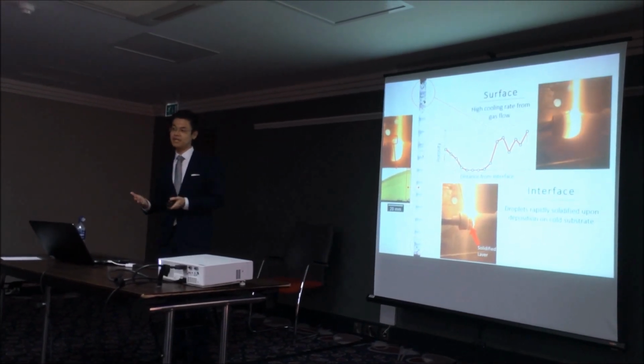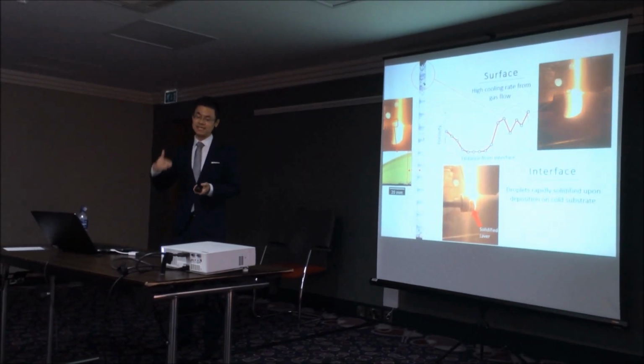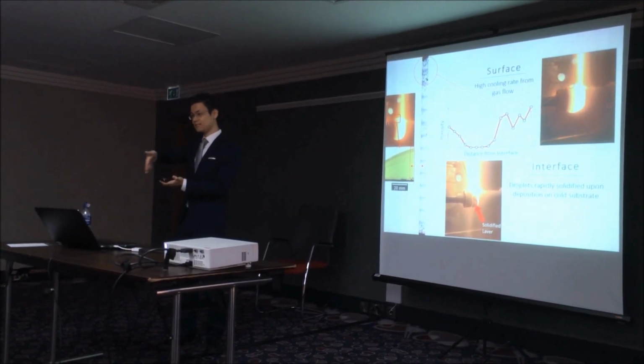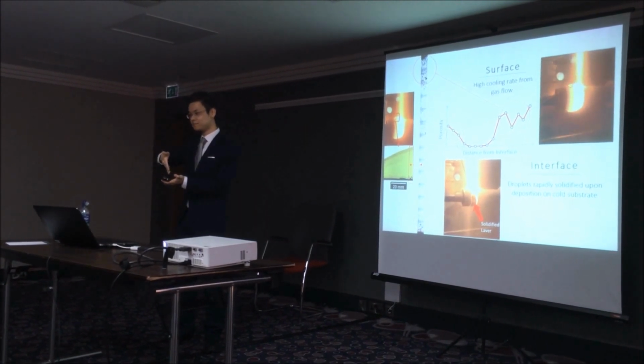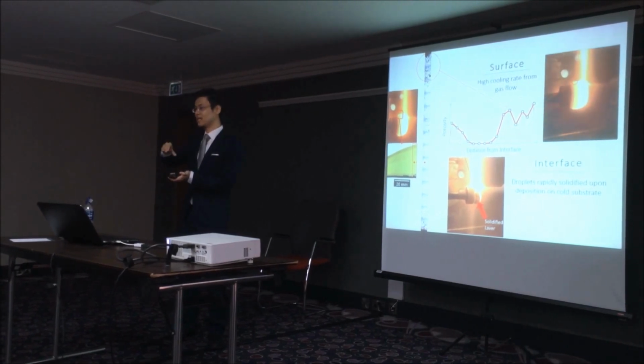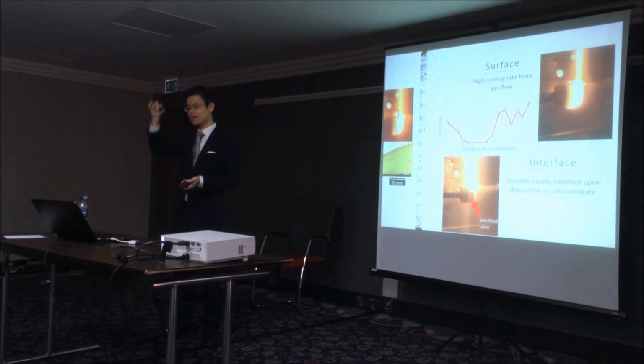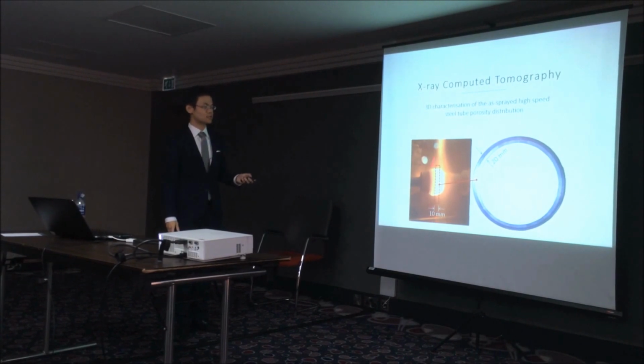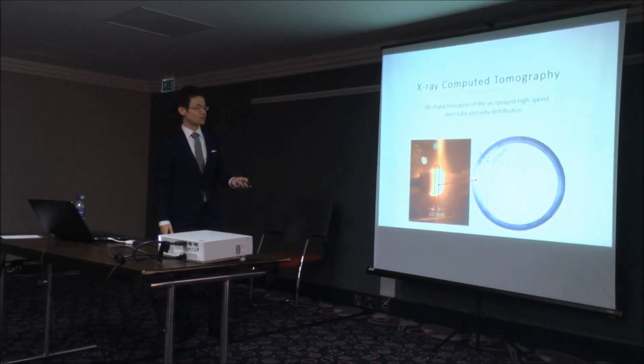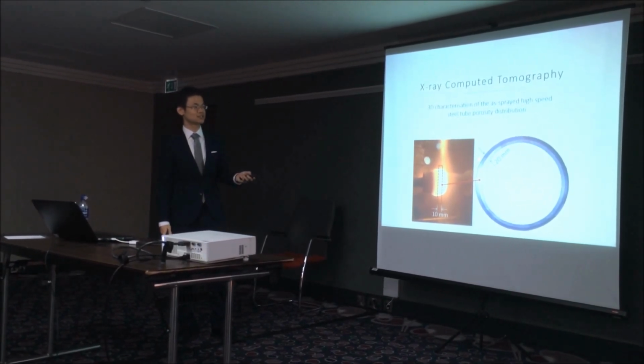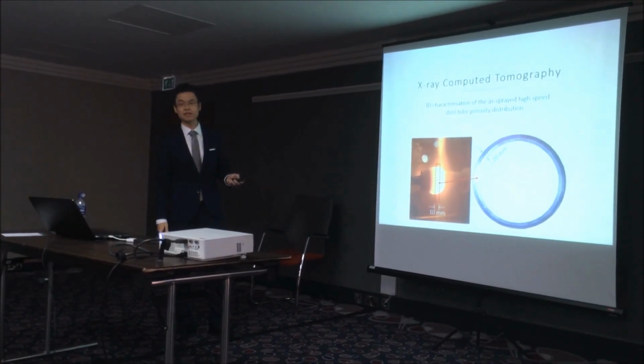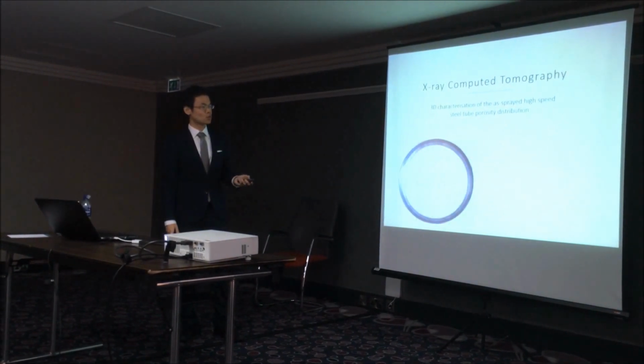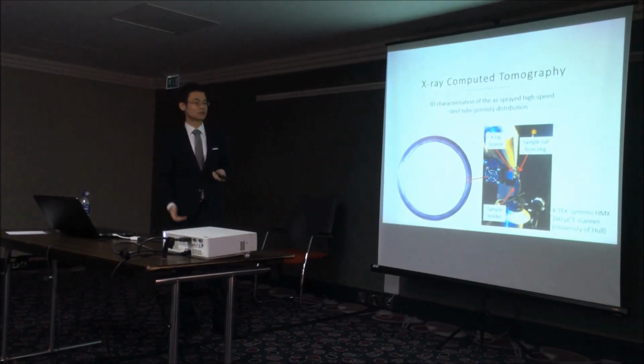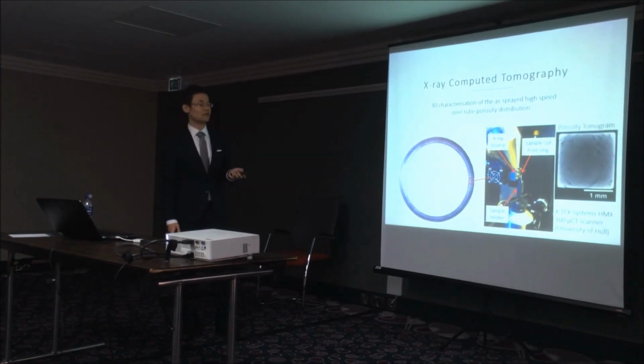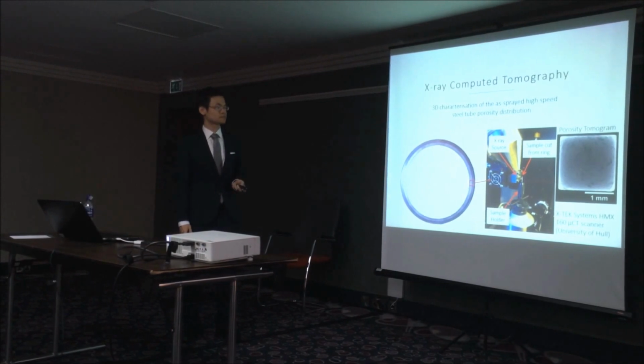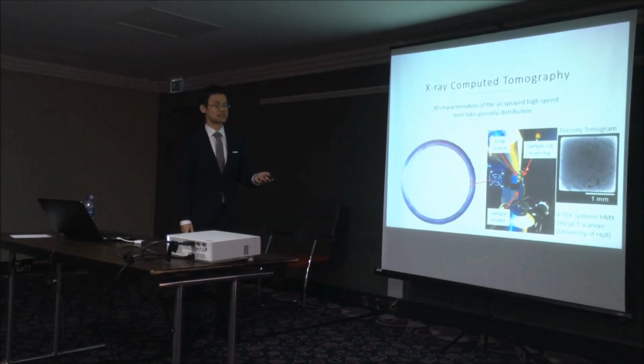So by controlling this process, we managed to manufacture a sprayed component with a step change in porosity by spraying in a multiple pass manner. The first few passes being a very hot spray to create the dense material, and the subsequent few passes being a relatively colder spray to produce a porous layer. And this is due to the reduced liquid metal hydrostatic pressure in the tundish. We then cut ring slices out of this component, with 10 mm wide and 20 mm thick ring slices. We then etched the rings to reveal the porous outer layer. Subsequently, we extracted samples to measure the porosity distribution across the thickness using X-ray computed tomography with one of our micro CT scanners at home. And this shows the porosity profile across the thickness of the ring.